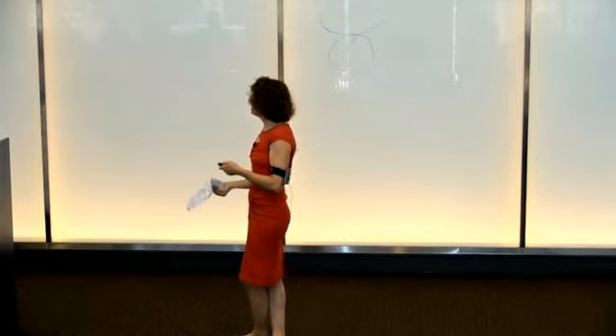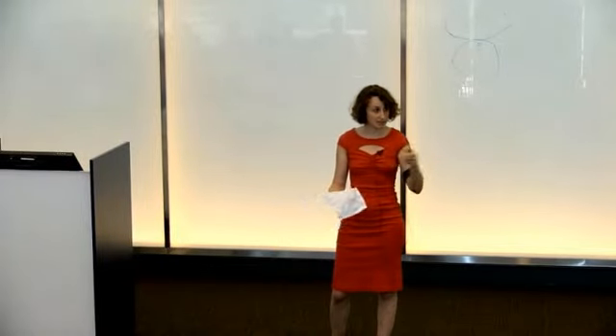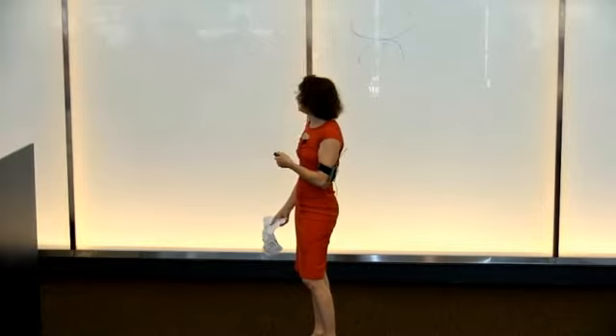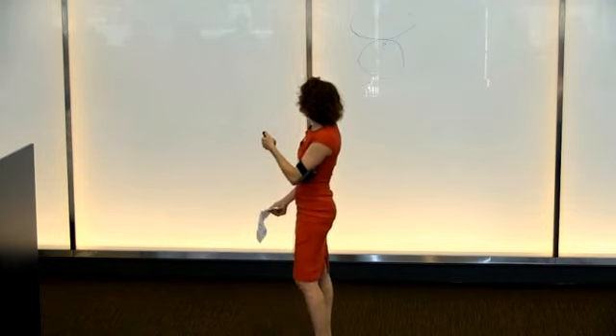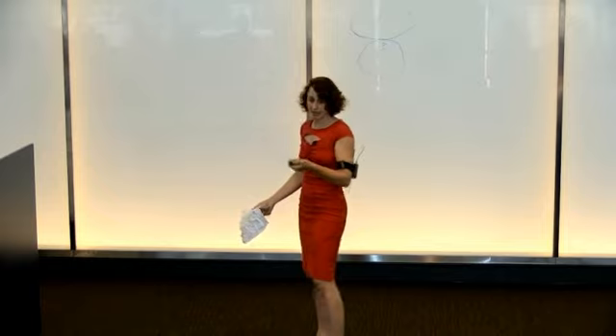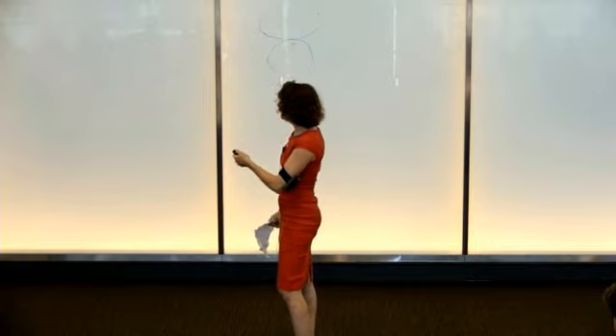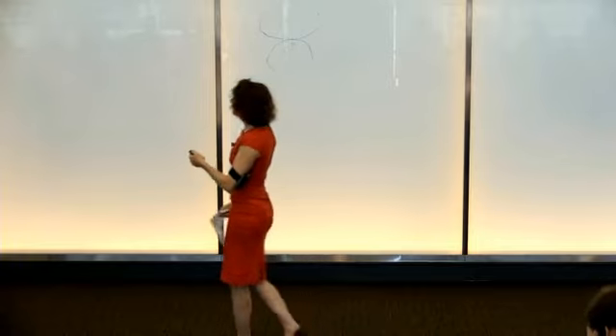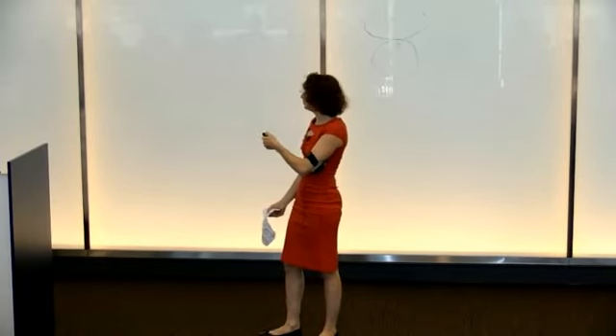In our case, we have n nodes. Each node has 3 degrees of freedom, so 3n degrees of freedom minus 6 for rigid body rotations and translations. And then compared it to the number of constraints, it's just the number of springs. So if I'm looking at one node, it has 6 springs. That's divided by 2 for double counting, meaning 3 constraints for each node. So 3 constraints, 3 degrees of freedom, sounds just about right for it to be stable, but the problem is we're talking about finite systems, meaning that at the edges we have missing springs. And the number of missing springs is going to be proportional to the perimeter of our lattice.